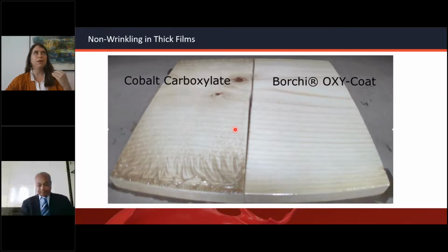One common problem with cobalt carboxylates is this wrinkling effect with high film builds. That comes from the fact that it is a quick surface dryer, so if you have too thick of a film and it cures on the surface, you have a lot of entrapped solvent causing wrinkling underneath your coating, as well as softness, poor stain resistance, lower hardness, a lot of issues in your coating. So Borchi OXY-Coat is very resistant to that because it's both a surface and a through cross-linking dryer. This brings you improved performance.